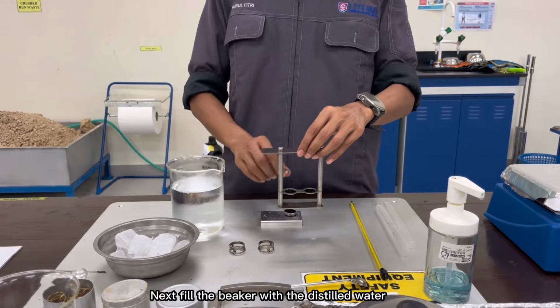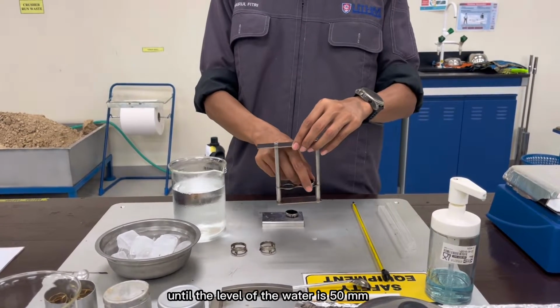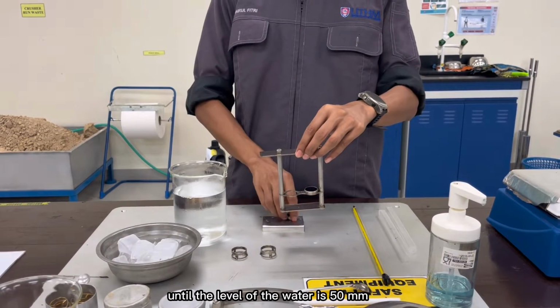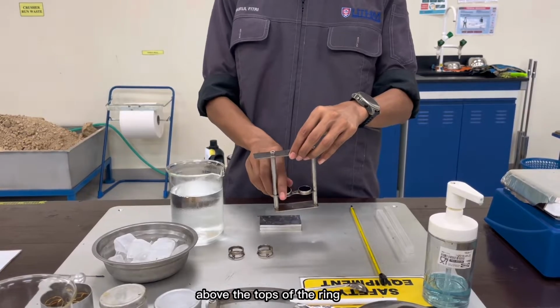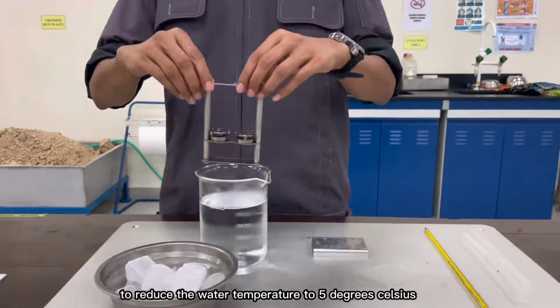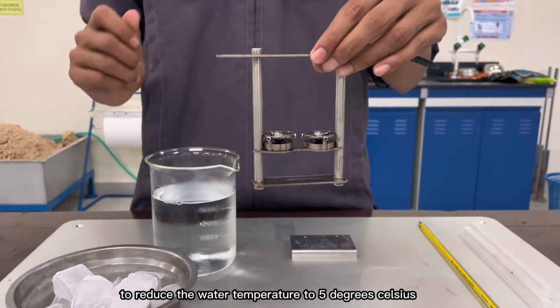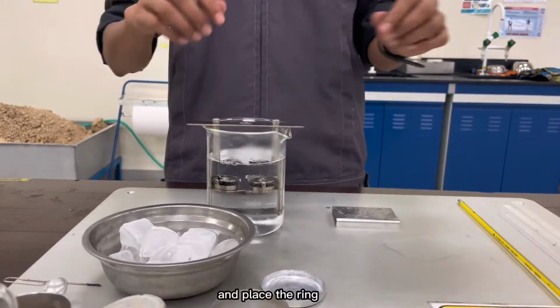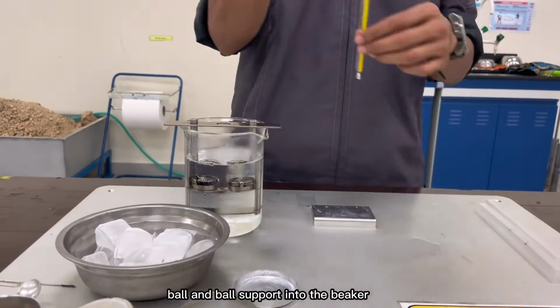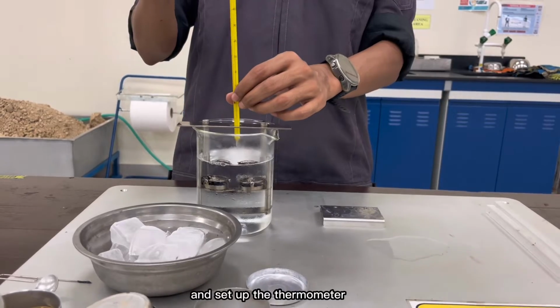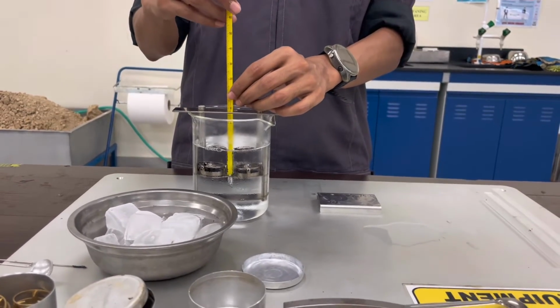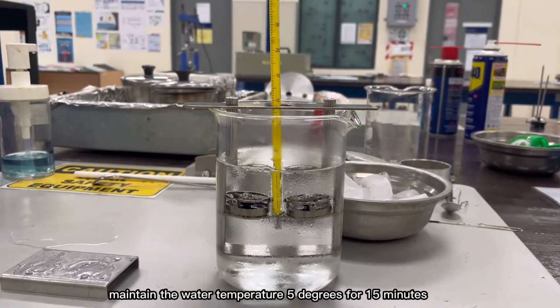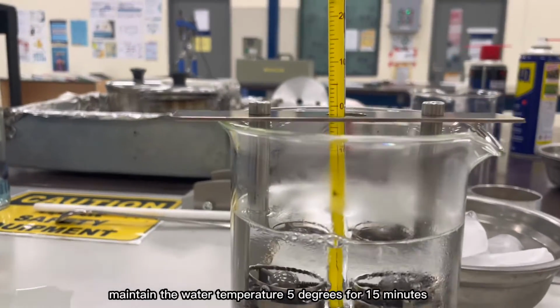Next, fill the beaker with distilled water until the level of the water is 50 mm above the tops of the ring. Insert the ice cube to reduce the water temperature to 5 degrees C. And place the ring, ball and ball support into the beaker and set up the thermometer. Maintain the water temperature at 5 degrees C for 15 minutes.